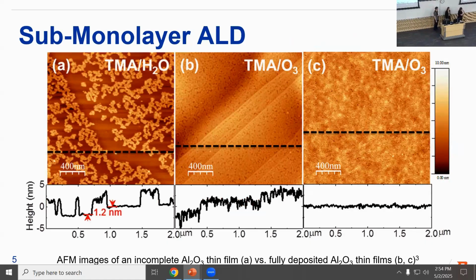So our project is more so looking to enable submonolayer ALD, which means that an incomplete monolayer is formed on the surface of the substrate, as we can see in image A, as compared to the fully deposited substrates in images B and C. Submonolayer ALD requires extremely small amounts of gas being inputted into the main chamber. So that is why we were looking at ultra-high vacuum environments for this. And it's important for research as it better reveals the reaction mechanisms behind ALD, allowing for better comparison to computational studies which involve one to few molecules interacting with a small portion of the substrate.